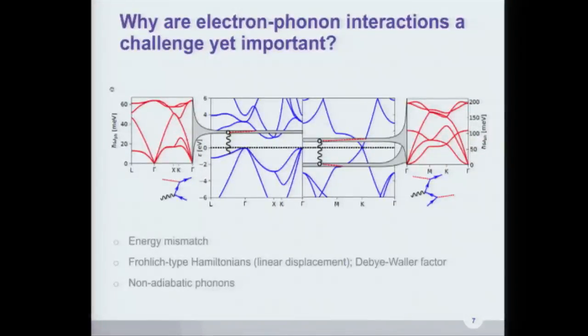And that's important because those types of couplings were previously ignored, both in the model Hamiltonian literature as well as, to some extent, in what is computationally implemented in most codes out there. We made an effort to include not only beyond Froelich-type Hamiltonians, the Debye-Waller factor, but really to start looking at non-adiabatic phonon contributions. And this gets into slightly tricky territory from both a theory and experimental standpoint.